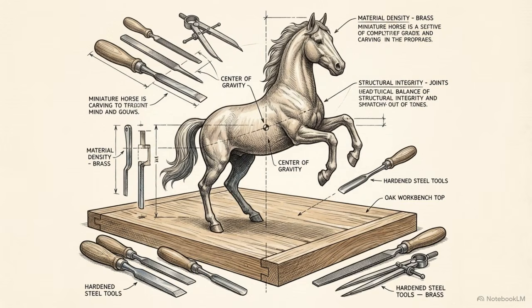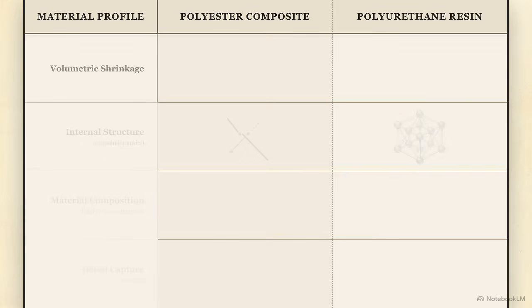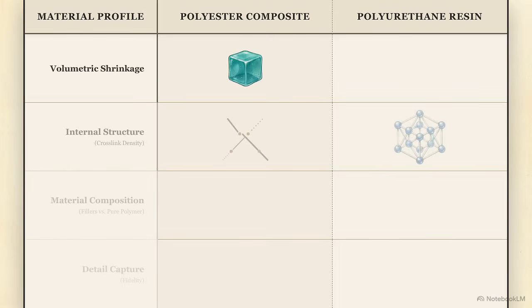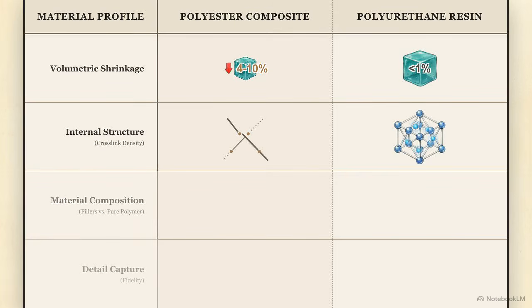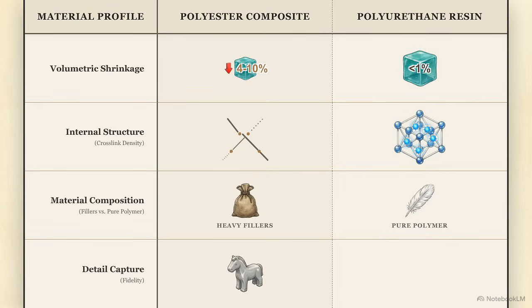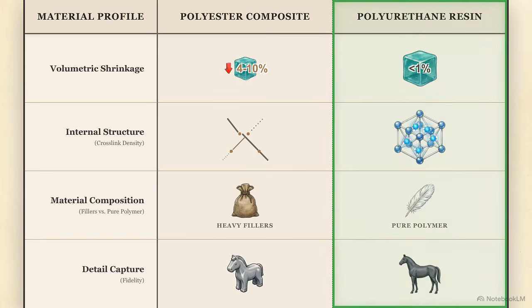That brings us to the exact material that built the model horse hobby from the 1980s onward: polyurethane. This material profile matrix directly compares our two options. Looking at the first row, the shrinkage rate for a polyester composite sits between 4 and 10%, compared to less than 1% for polyurethane. The underlying chemistry explains this difference. Polyurethane forms a highly controlled cross-link density during its cure. Cross-link density refers to the number of chemical bonds connecting the polymer chains, which dictates how rigid and stable the final structure will be. Because this highly cross-linked cure is inherently stable, polyurethane requires no heavy bulking fillers. It produces a strong material without the brittleness found in polyester.